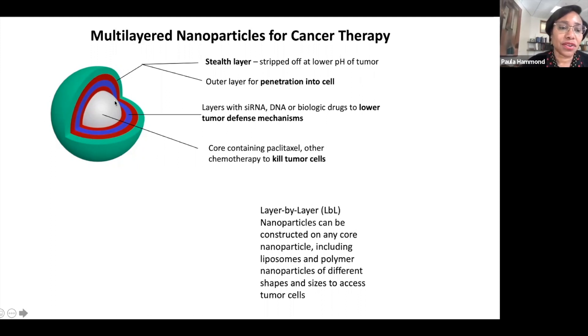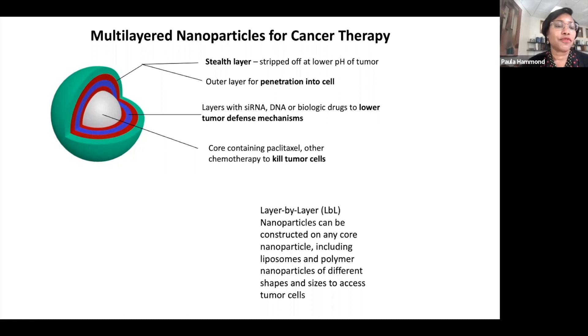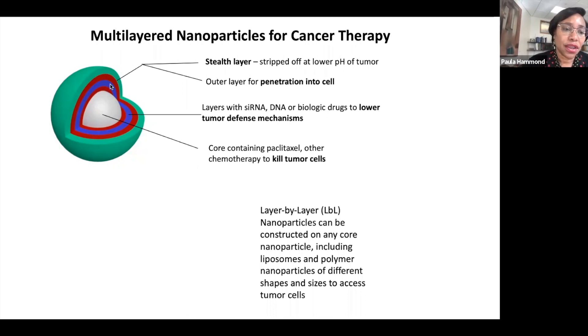We have to protect that siRNA, so we put down another positively charged layer. Because a positively charged nanoparticle will be rapidly cleared from the body — due to its tendency to absorb large amounts of protein and be recognized by monocytes and other immune cells — we need something on the outer layer. We add a final outer layer that is strongly negatively charged, giving us net repulsion from mammalian cells that have negatively charged glycans on their surface, plus a high degree of hydration that lowers the thermodynamic driving force for protein adsorption. We also want this outer layer to help direct the nanoparticle to the tumor cell.